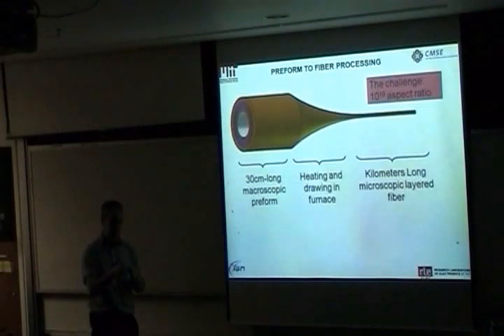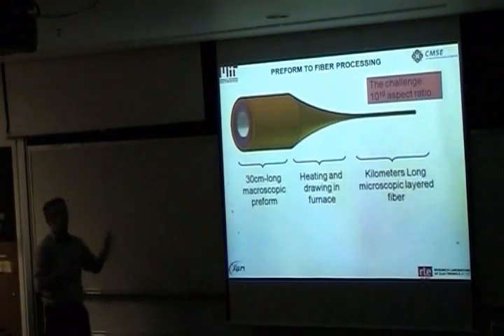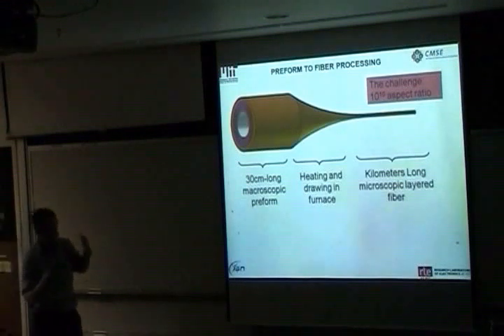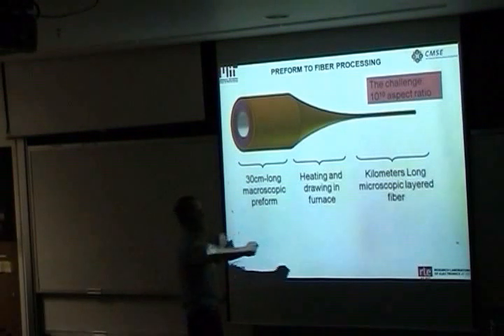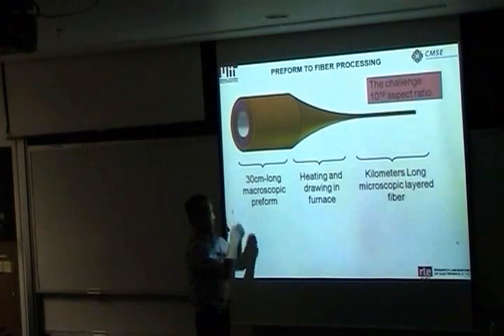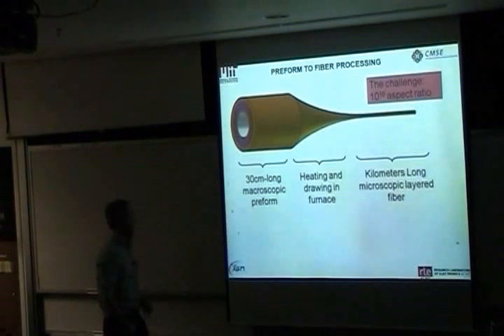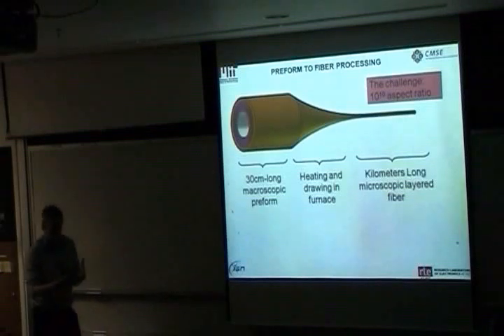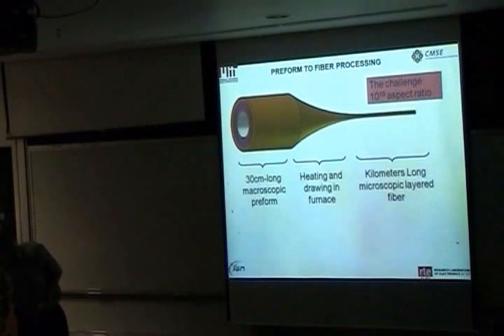And so then the challenge became, well, how in the world are you going to make fibers at kilometer length scales with features that are sub 100 nanometers, maybe even a micron? People know how to make micron layers on wafers or on substrates, but how are you ever going to do it on the inner part of a fiber? If you think about it, achieving uniformity over a kilometer length scale while controlling features down to well below 100 nanometers gives you a challenge from a processing and fabrication standpoint that is on the order of 10 to the 10. So that was the problem.